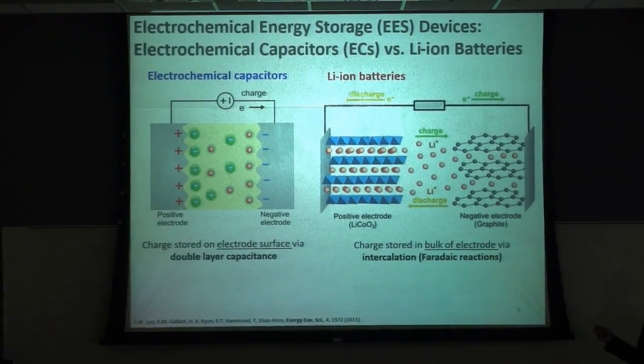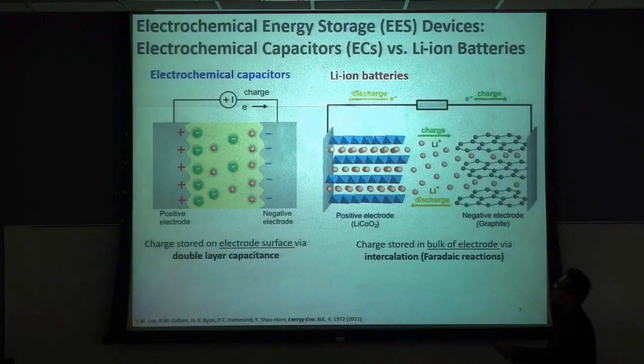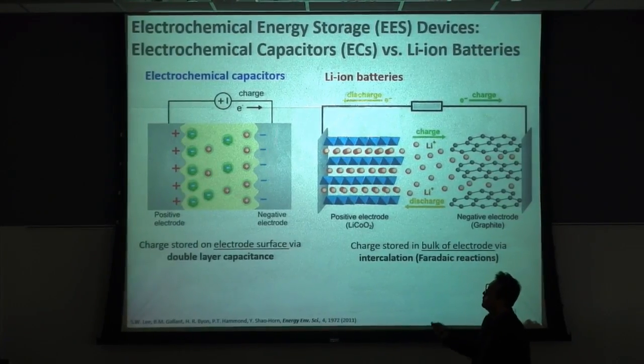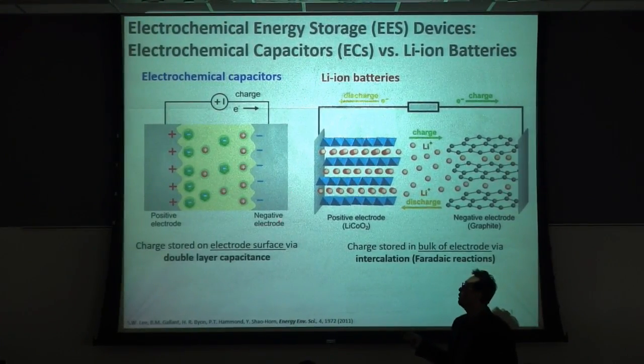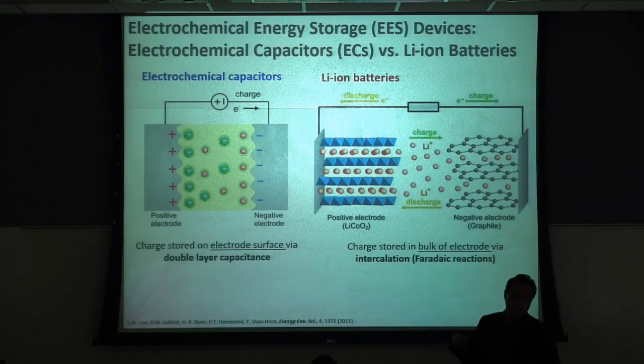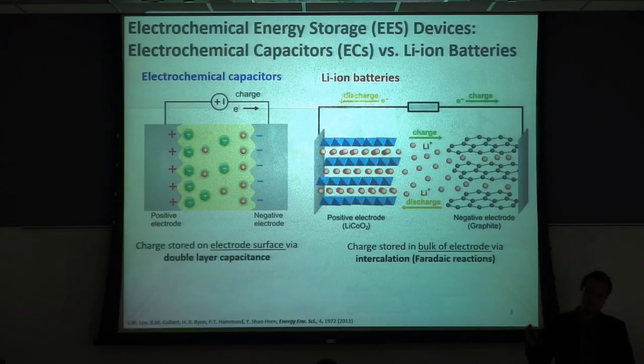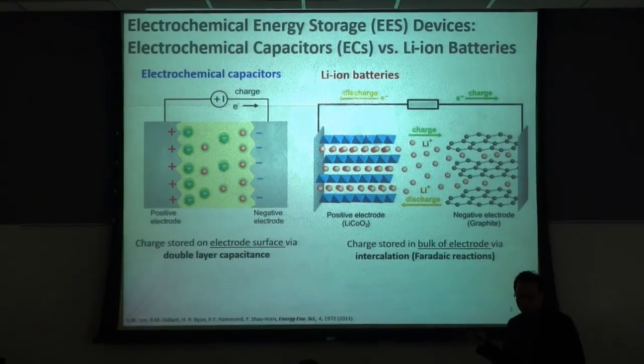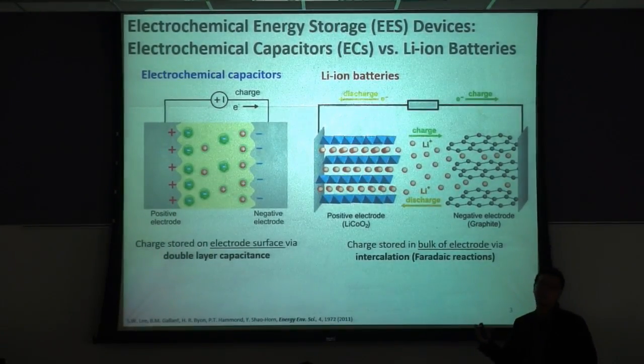So when you apply the potential, one electrode is positively polarized and the other one is negatively polarized. Then oppositely charged electrolyte ions can adsorb on the surface of the electrodes by electrostatic interaction. So we call this a double layer capacitance. Basically, this kind of electrochemical capacitor can store charge on the surface of the electrodes through this double layer capacitance charge storage mechanism.